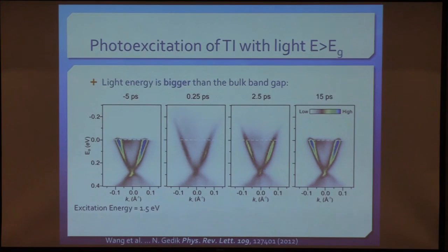It turned out that they cannot directly couple to each other. They cannot scatter from bulk to surface because of kinematics. You cannot conserve energy and momentum. They have different dispersion. But they actually talk via phonons. The way we figured this out is we did this experiment at room temperature and at low temperature. They came into equilibrium quite quickly at room temperature because there are a lot of phonons around. But at low temperature, it takes quite a bit of a while.